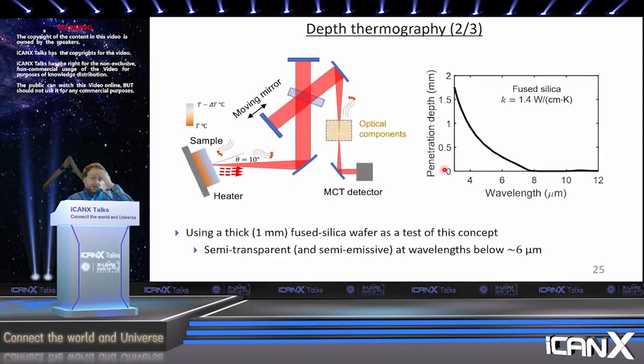The way that we demonstrated this is using a very simple setup. We have a heater stage over here. We control the temperature of our sample, and we have a sample that is relatively thick. In this case, it's 1 millimeter thick, and again, it's this fused silica wafer. The reason why we use the fused silica is, first of all, it's semi-transparent in the relevant wavelength range. You can see that between, for example, 3 and 8 microns, the penetration depth is on the order of 1 millimeter, but also changes with wavelength, which is important for us to be able to extract useful information.